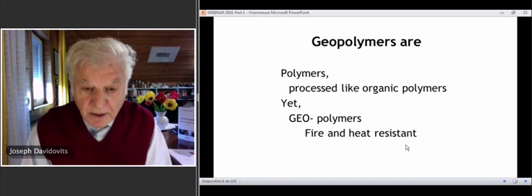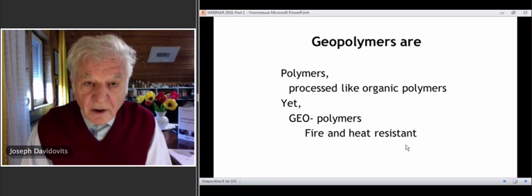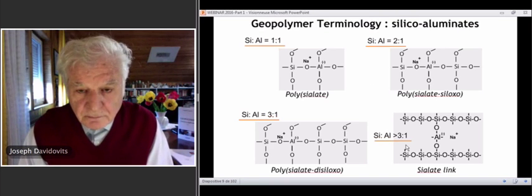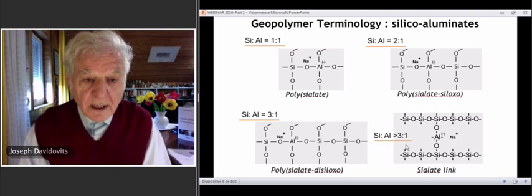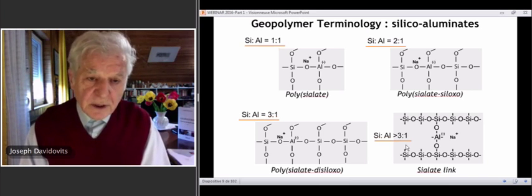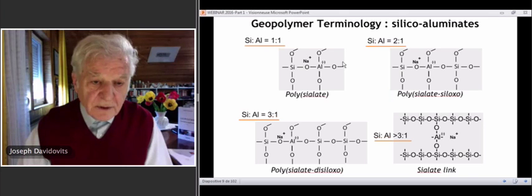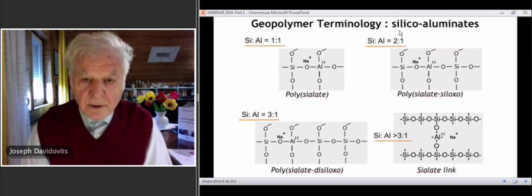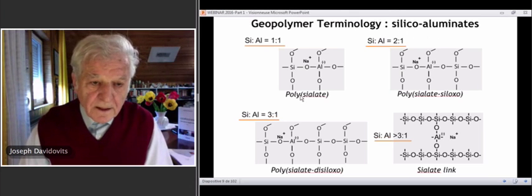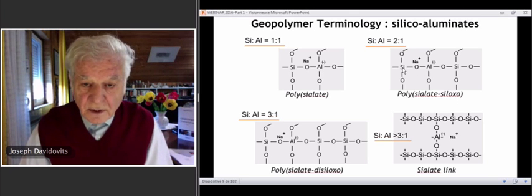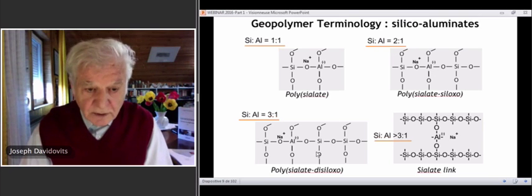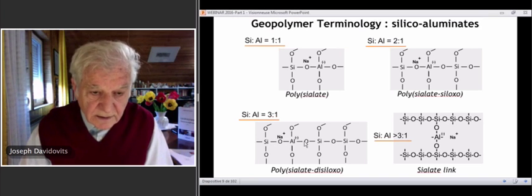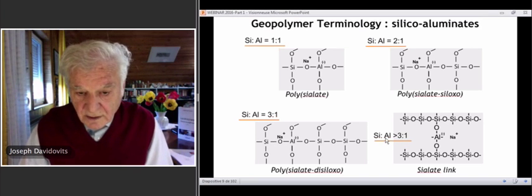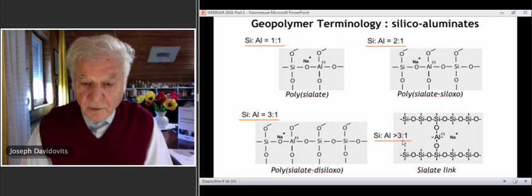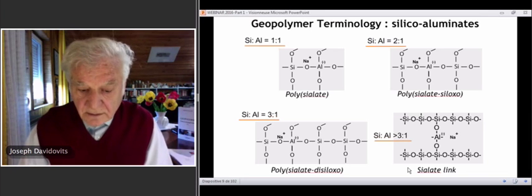Since they are polymers, they have a polymeric terminology. Otherwise they would not be polymers. Every polymer has a very special terminology that relates to its chemical makeup. So we have here the geopolymer terminology, for the field of the silico-aluminates: polysialate with Si:Al 1, Si-O-Al; polysialate-siloxo, Si:Al 2; polysialate-disiloxo, Si:Al 3, so we have the sialate and the disiloxo. And for Si:Al ratios higher than 3 to 1, I introduce the sialate link.